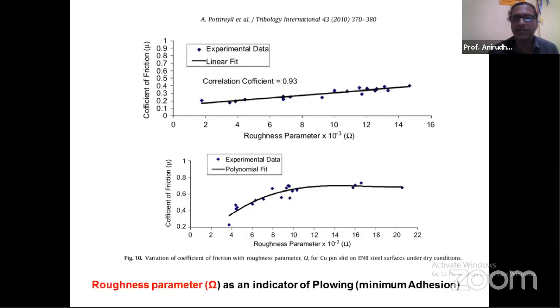We did correlate this with experiments under dry condition also, in which case it doesn't follow a line, it follows a curve. We have explained why it follows a curve and why this pattern is followed, based on another parameter called plasticity index, which comes into play during rubbing under dry conditions. So the bottom figure, which doesn't show a line but shows a curve, is actually for dry experiments, and we have explained this also in our paper.